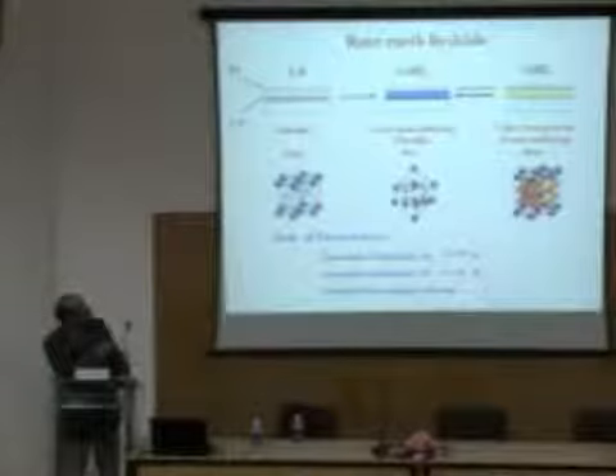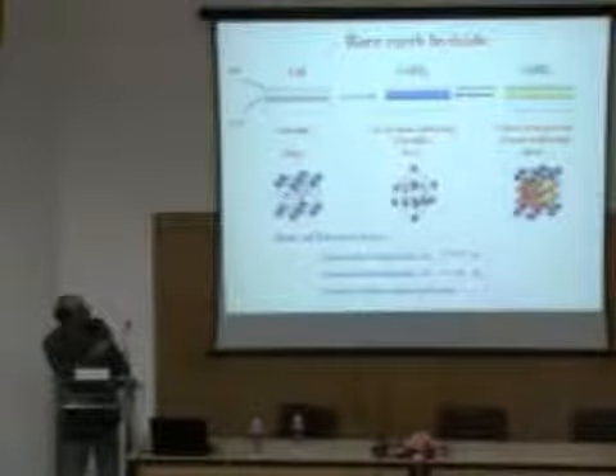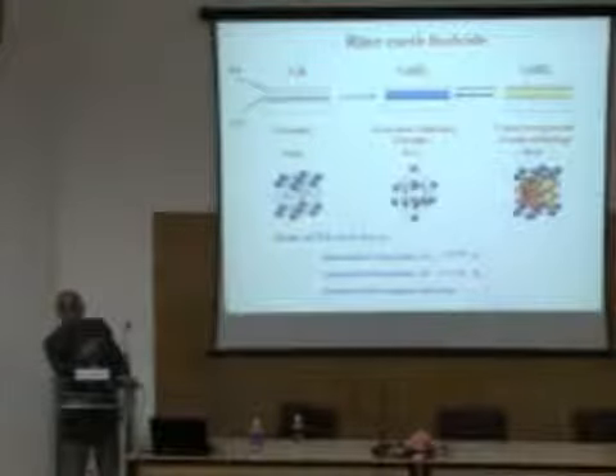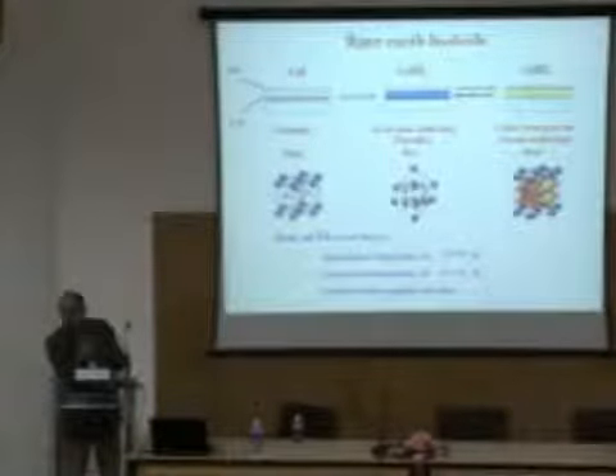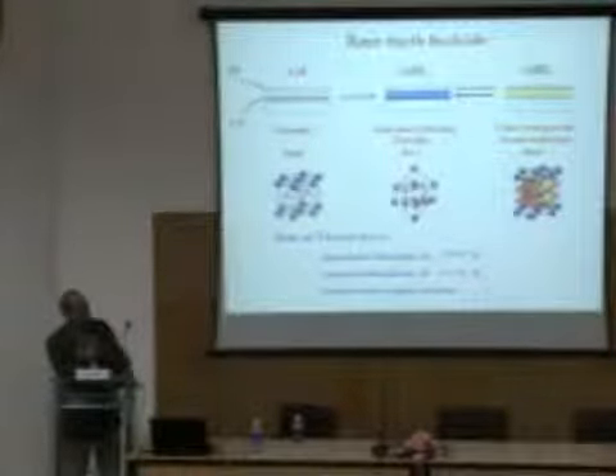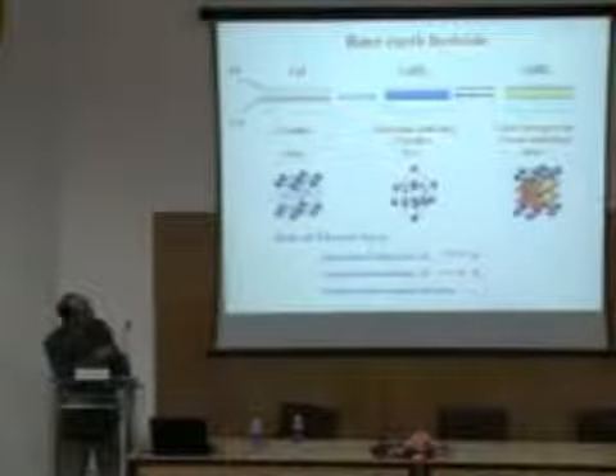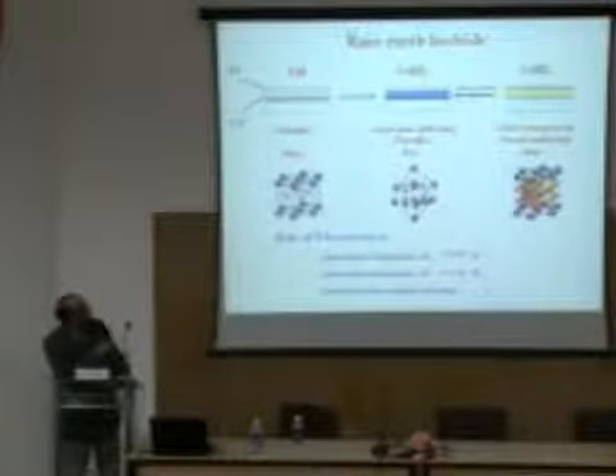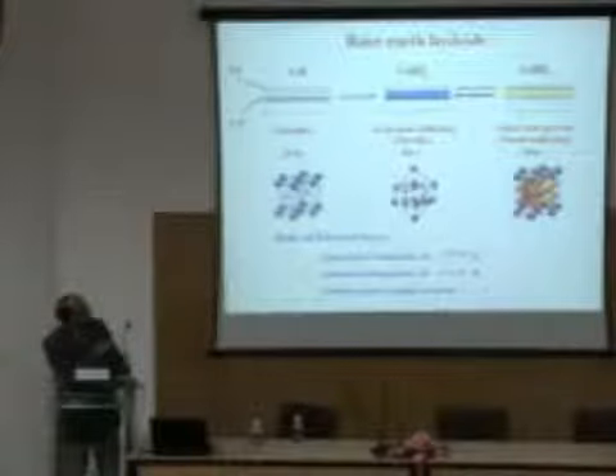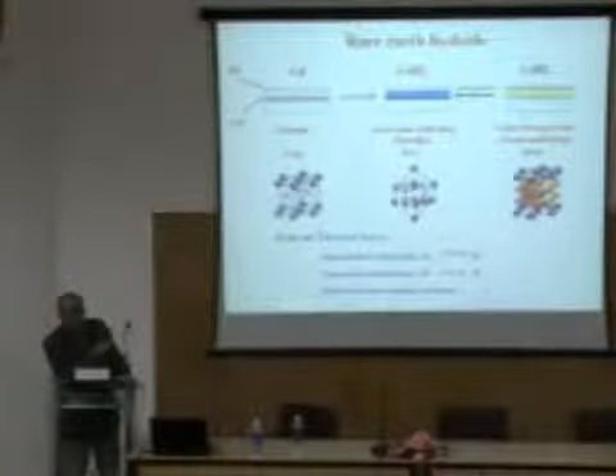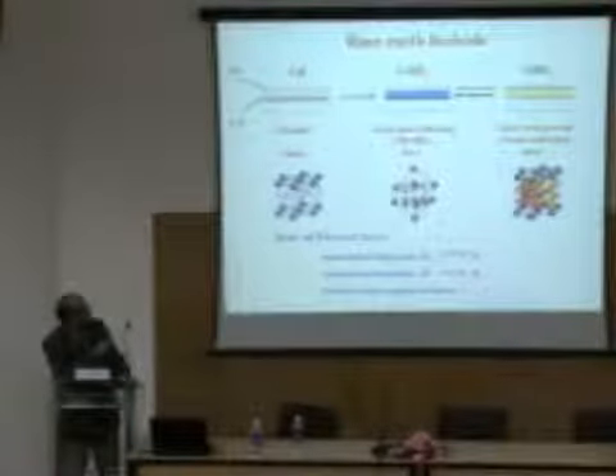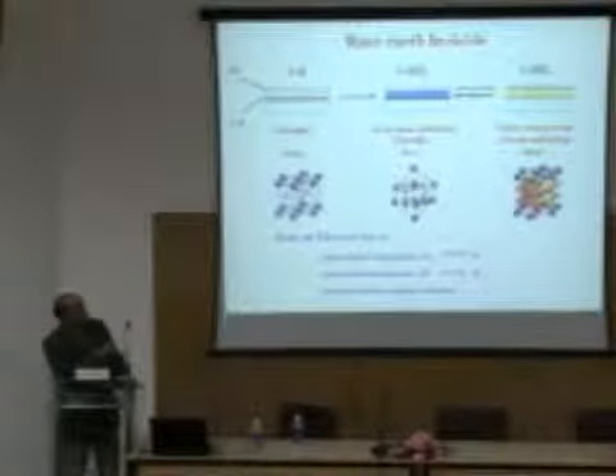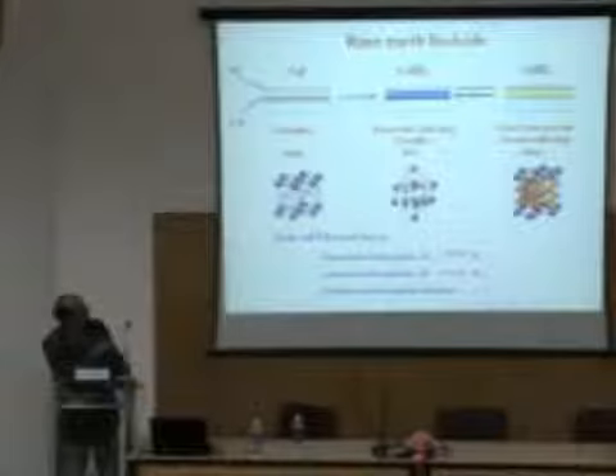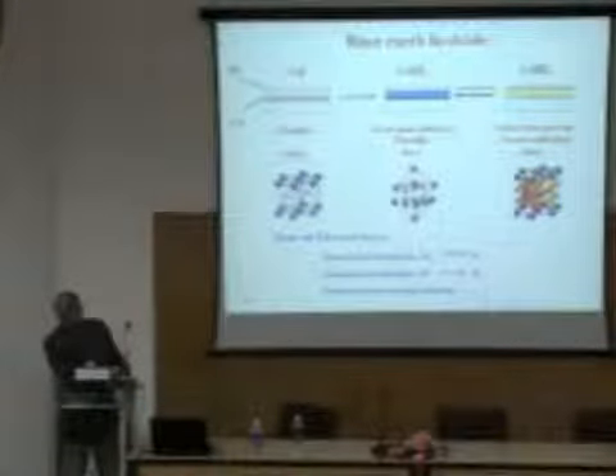When it goes from metallic, it is still metallic, but there is a change in the color. Gadolinium dihydride is blue in the reflection mode. If you see this material in reflected light, it will appear blue, but you can see that there is a crystal structure transformation. The material has already changed its crystal structure. The rare earth metal gadolinium was HCP, hexagonal close-packed, crystal structure. Gadolinium dihydride is FCC, face-centered cubic.